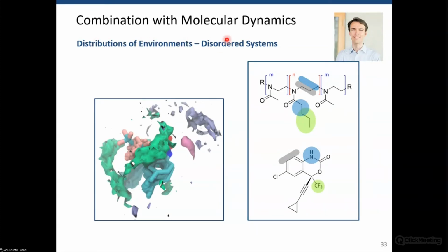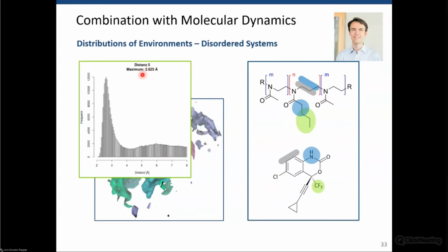And maybe we can represent these disordered systems by also getting a distribution of environments from molecular dynamics. You can see here the first attempt of simulating the whole micelle. And then what we did from this simulation is we wanted to extract individual parts and countercheck them. We found the closest distance also to be between these two groups, so in agreement with our NMR measurements.